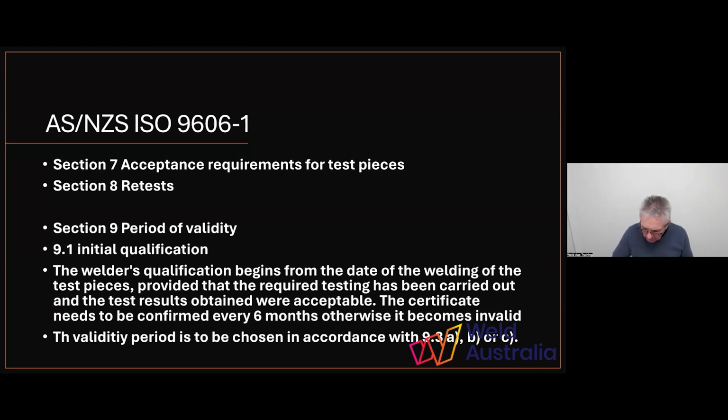All right. So 3834 is one of those quality standards that a lot of companies are going down the pathway, and that gives you strict regulations and naturally being operators qualified to 9606. But it says there, basically, you just got to provide evidence that they're welding continually to a certain quality. So most of our standards will often say, if you're going to go down the 3-year pathway, Aaron, let's say, for instance, you've got to provide some evidence of every 6 months, some form of an NDT report to back it, is the way.